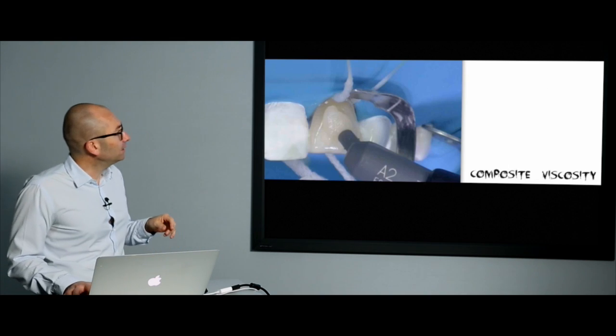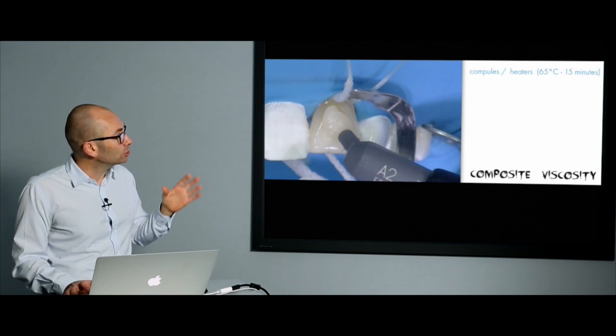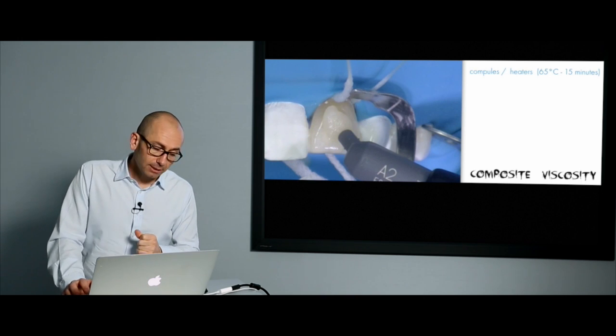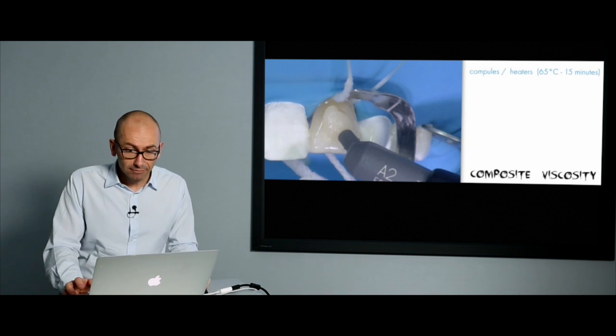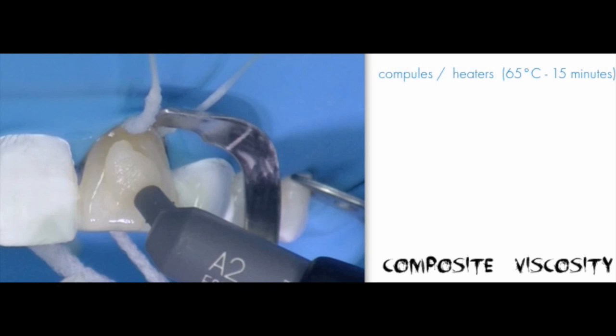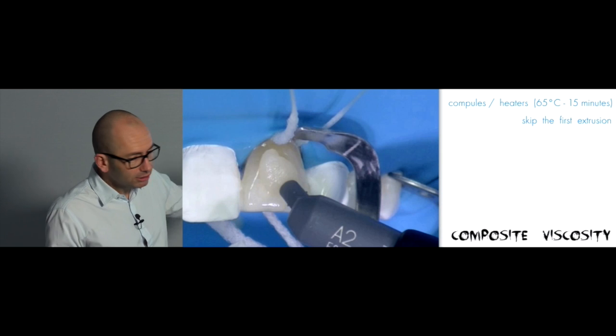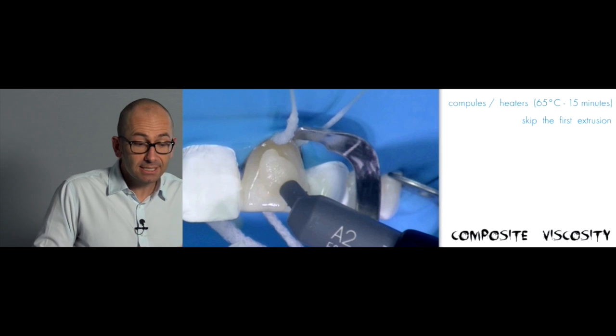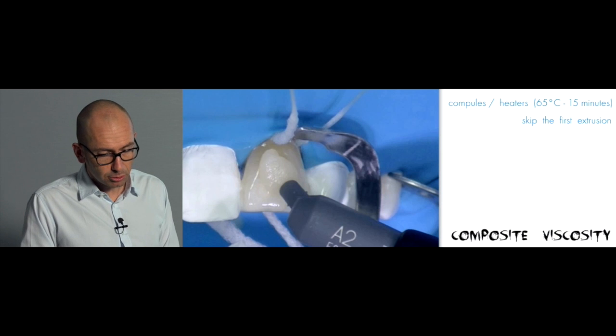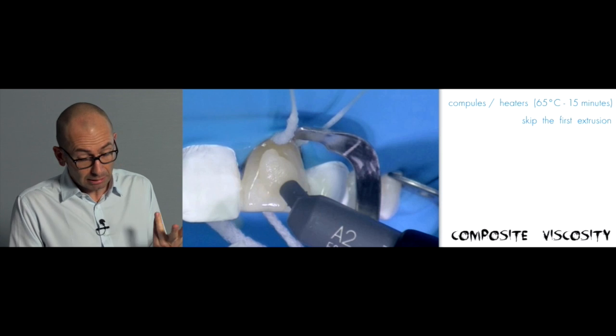A good tip to keep in mind is that you just have to heat your compules very high, and some people are scared about this. 65 degrees, what the hell, you will just cook the pulp. No problem, because you take 65 degrees and you have 10 seconds to get it in the mouth, and it's maybe 40 degrees at that time, so no problem with this. You have to prepare that heating 15 minutes before the cementation, and please get rid of the first extrusion of the product, because it is not so hot at the very top of your compule. So skip the first extrusion, which is a little bit more viscous, so it can create some problems.